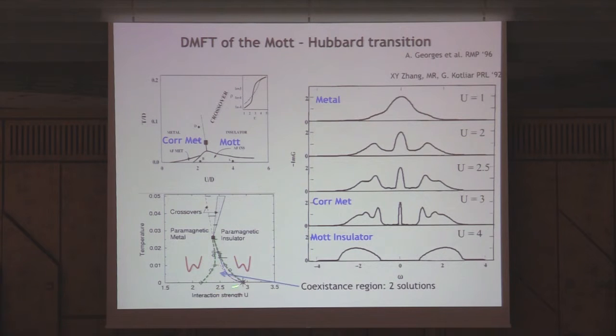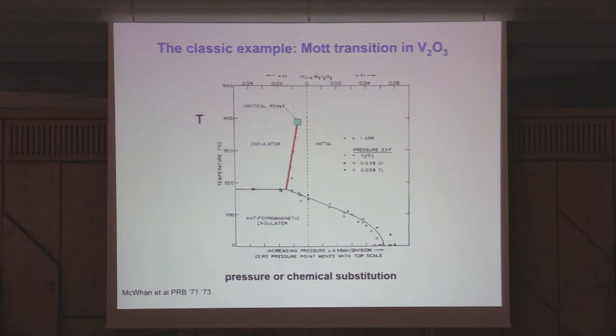Okay, since here you have a region of coexistence, you have to compare the free energy in order to decide which is the true solution of the model, and that gives place to a first order line. So when you put that back in a model with some finite frustration, you can find all the same topology as in the V2O3 that I was mentioning a moment ago, where this first order line ends in a second order critical point. Above that, you have crossovers, and at low temperature, you have different antiferromagnetic states. So you have a correlated metal and an insulator, and an important thing is that this correlated metal, you can destroy it by heating. So this is the V2O3 phase diagram, which corresponds to the previous one.